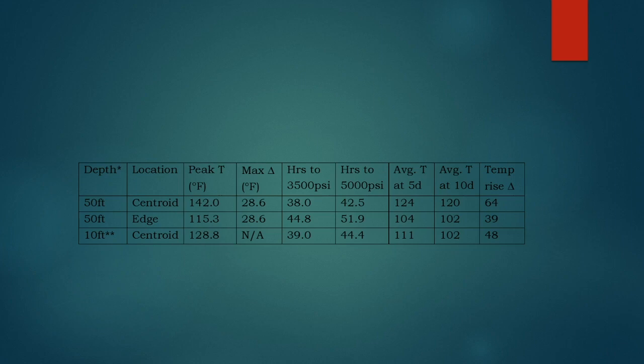where we had the temperature at a depth of 50 feet, 50 feet of concrete. The centroid, the peak temperature was 142 degrees, well within the maximum temperature that they could experience. So they were well within that. The mix design was working beautifully. The edge, which is right along the side where the earth is, was only 115 degrees. So the maximum delta between the centroid and the edge was about 29 degrees Fahrenheit, a little bit below that, which means that again, the mix design is doing exactly what it's supposed to do. You're not going to have too much thermal stresses.